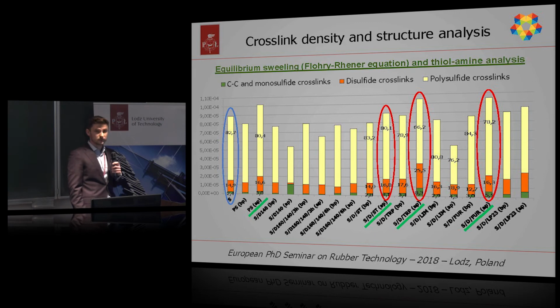So looking at the results, we can gather that sulfur organic copolymers, before and after purification, are taking part in the curing process, and in some cases lead to vulcanizates with higher crosslink density than the reference sample, which was cured with orthorhombic sulfur.